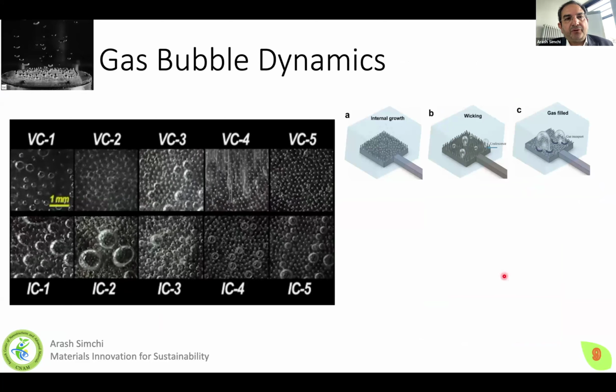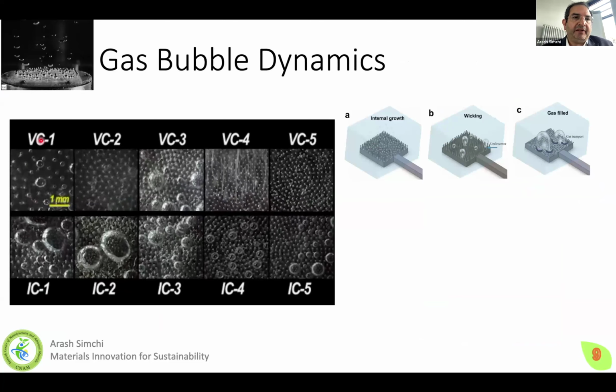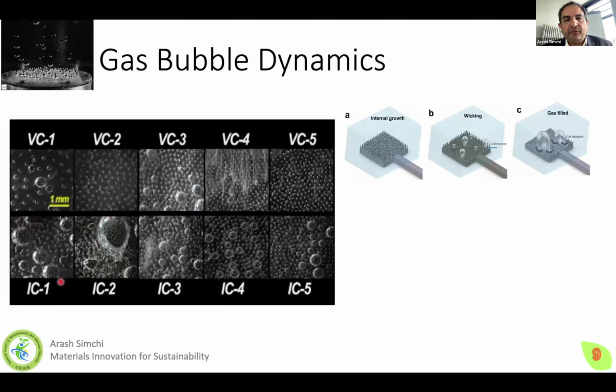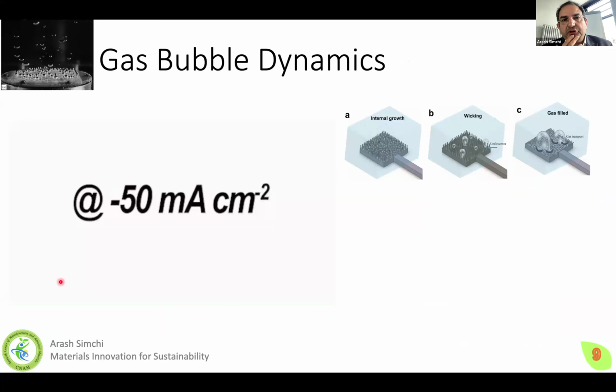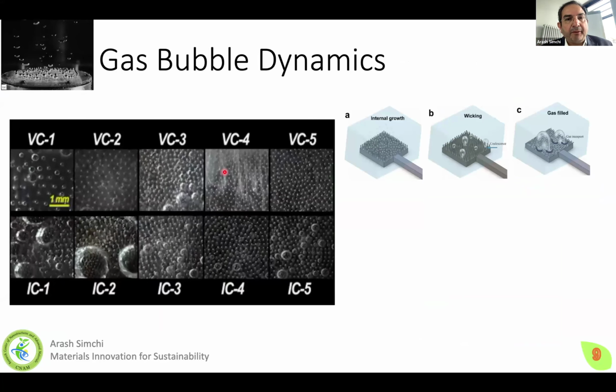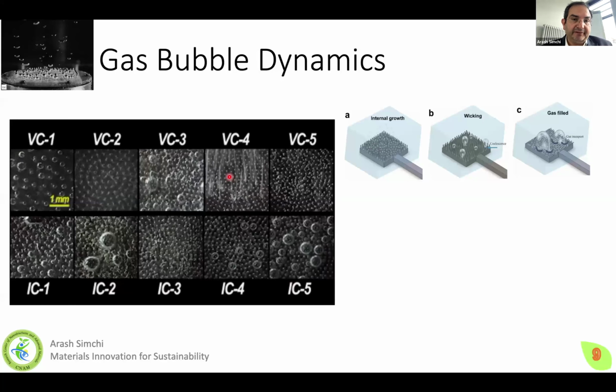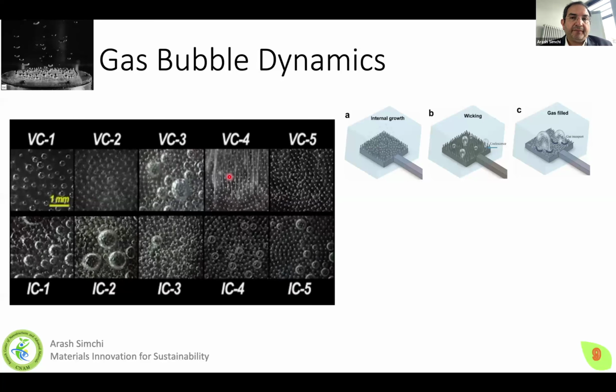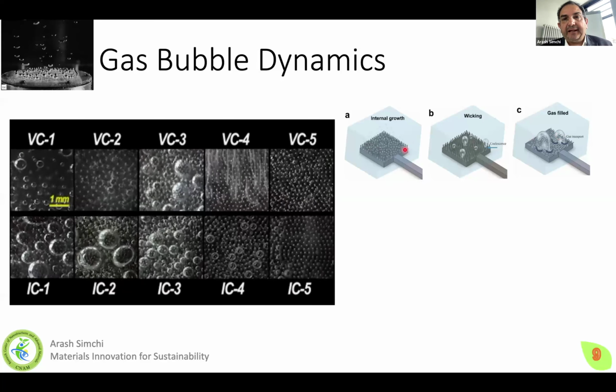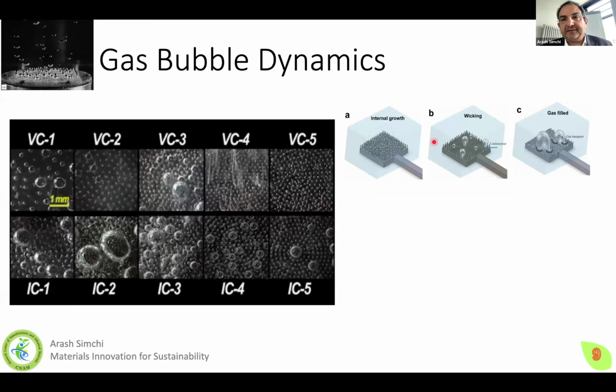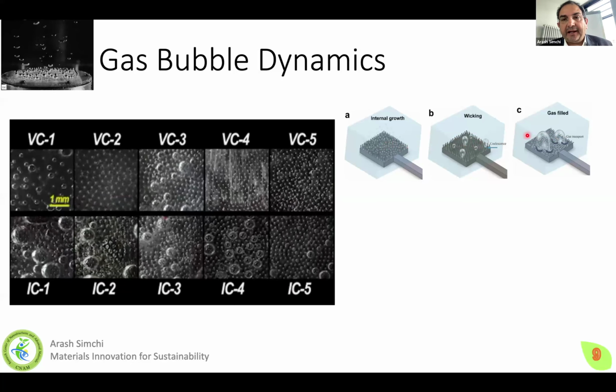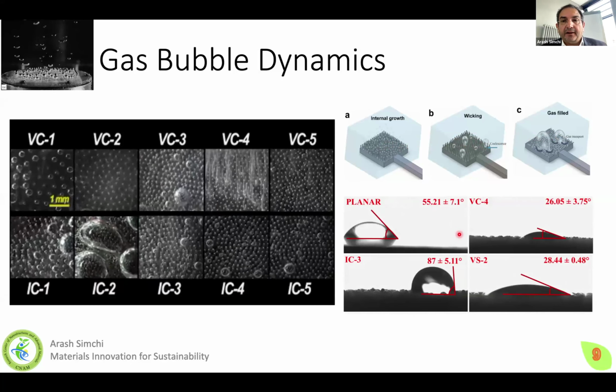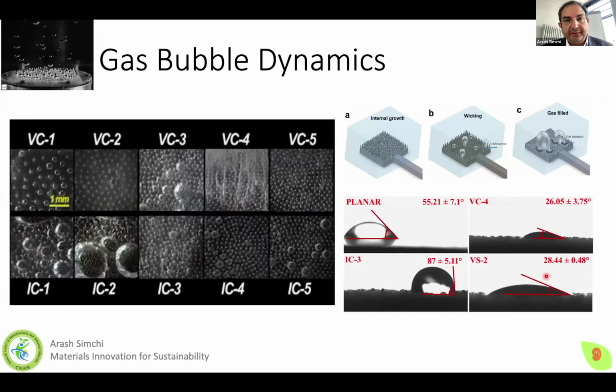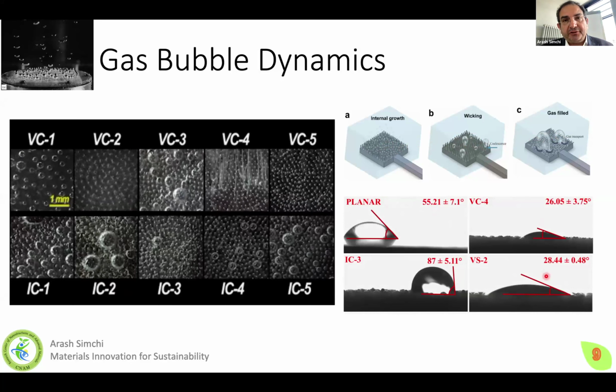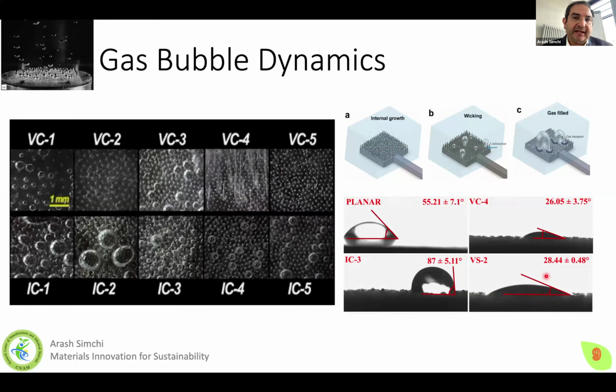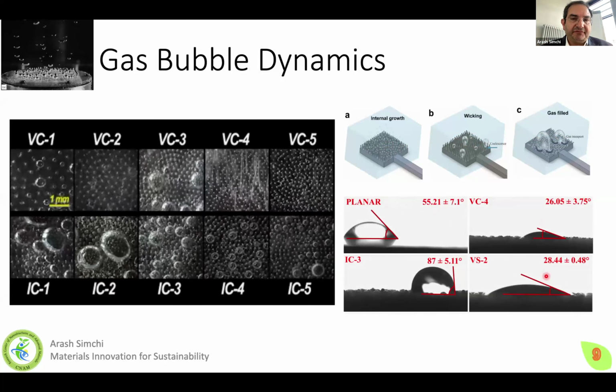As you see here, don't care about these numbers, just V means vertical, IC means inclined, with different density and different configuration. I just want to show the concept. As you see, the bubble formation rate is completely different when we use different geometry. And then we develop a model, say, okay, the kinetics of gas release depends on the configuration. And we found that it clearly depends on the surface tension. Otherwise, we change the apparent surface tension of our electrode by geometrical effects.